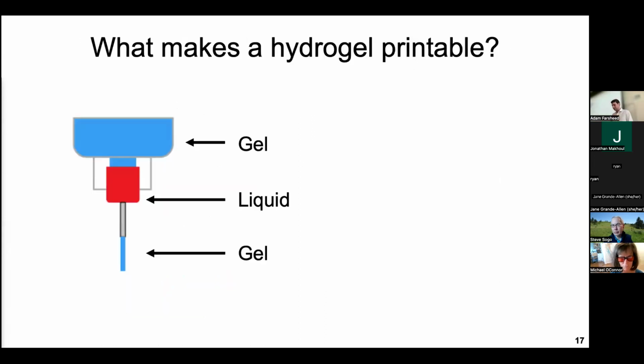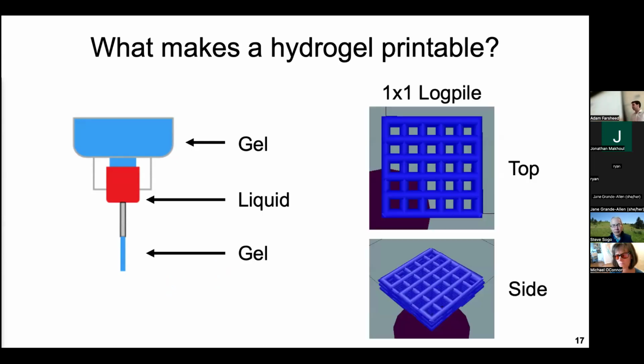So now the question is, how do we print this material? Well, it has to have a very unique set of properties, because for these hydrogel materials, the way that we print them is we basically prepare them as a gel, and then we push on them really hard so that they flow as a liquid. And we design them in a way so that as soon as they stop flowing, they re-gel. And this self-assembly, again, of MDPs is what is going to allow this to occur.